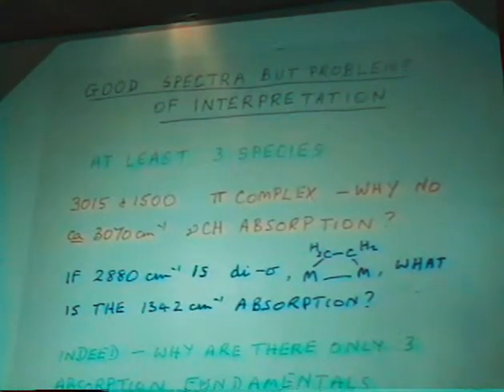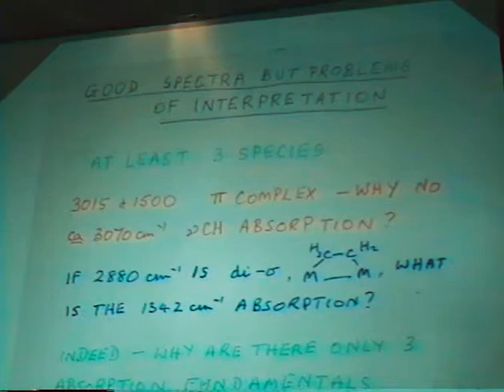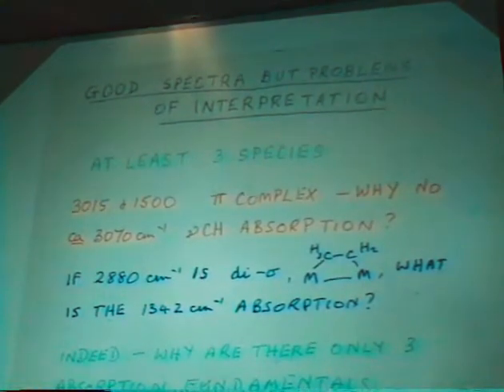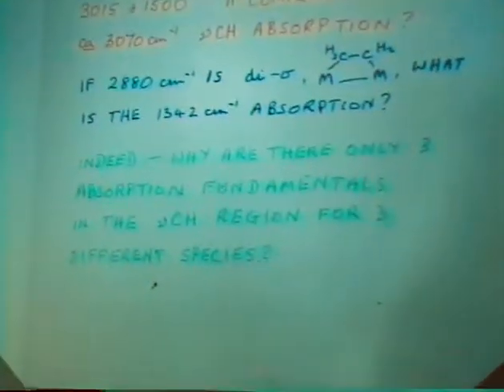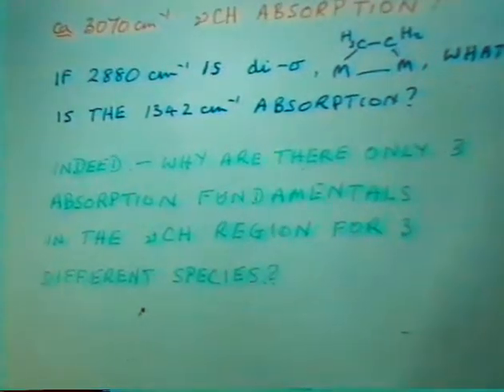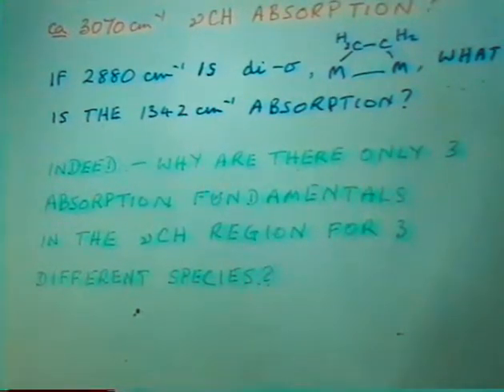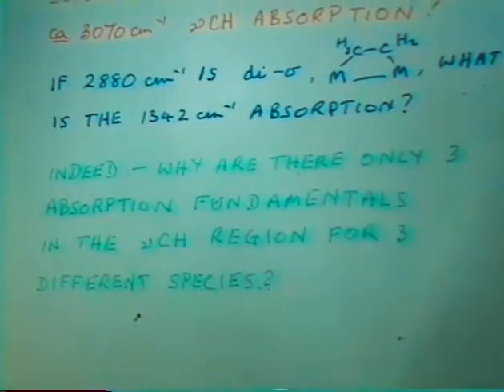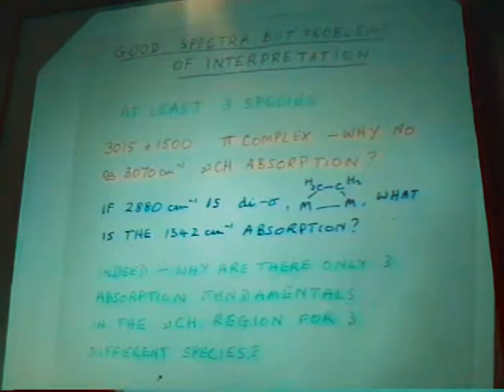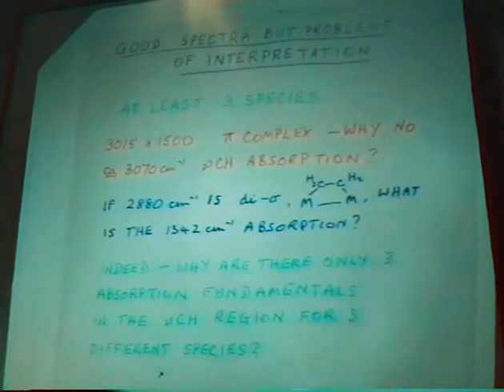Why didn't we get that 3070 absorption band, which we had been expecting? And if the 2880, the strongest band, is the di-sigma, what is the 1342 absorption? It was difficult to attribute it to that. And anyway, we have three species, and we only have three CH stretching fundamentals. And at least two of the species must each have four CH bonds. What was going on? And we were really rather baffled.